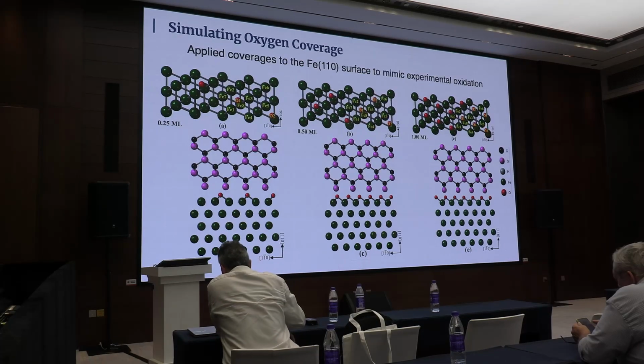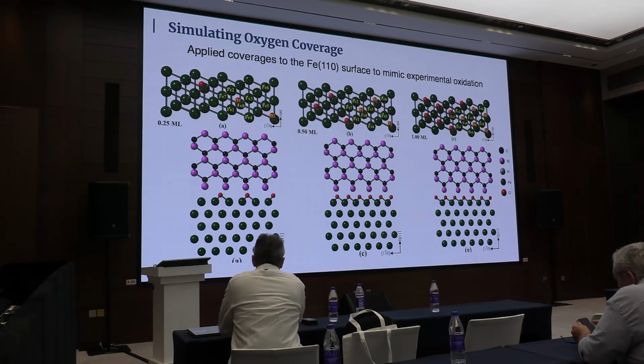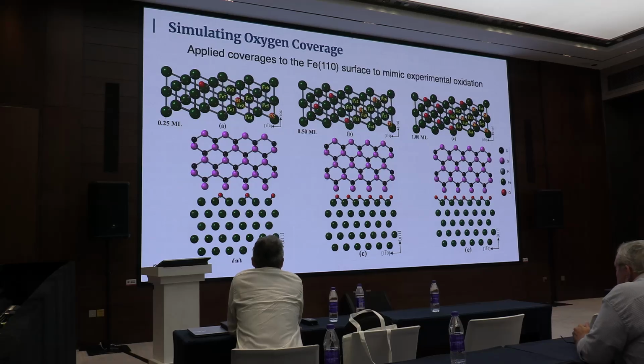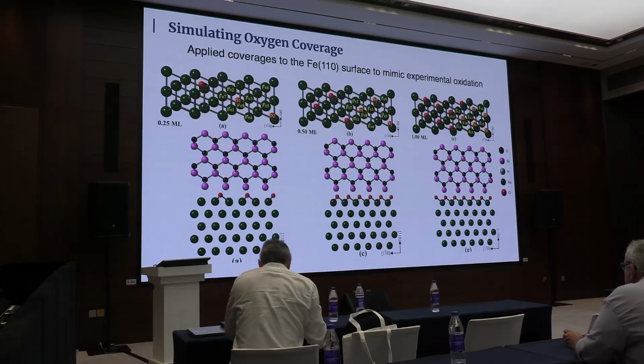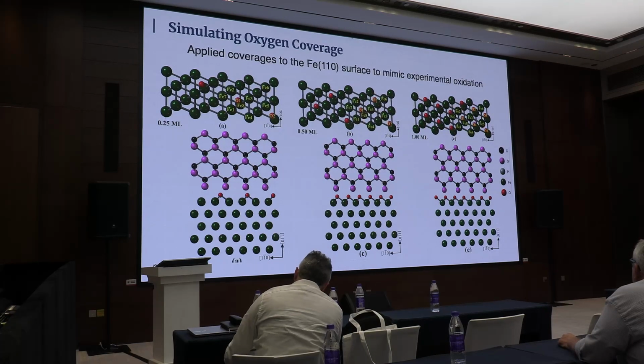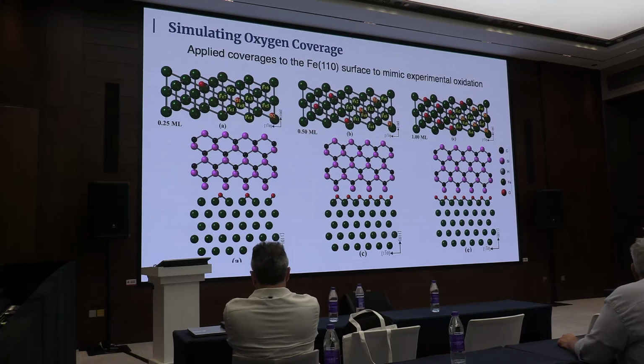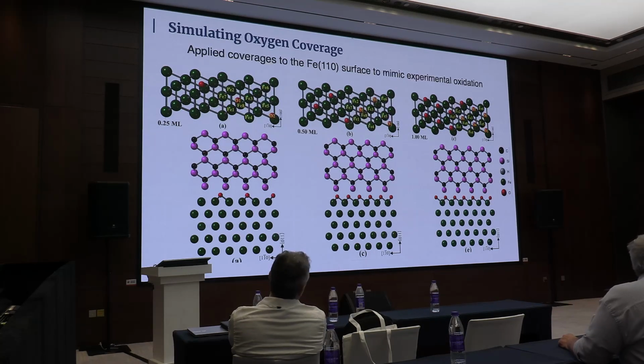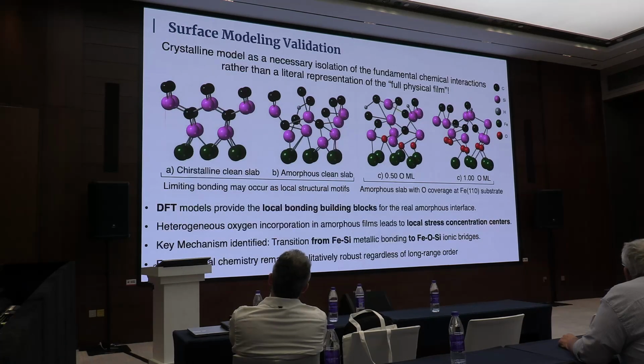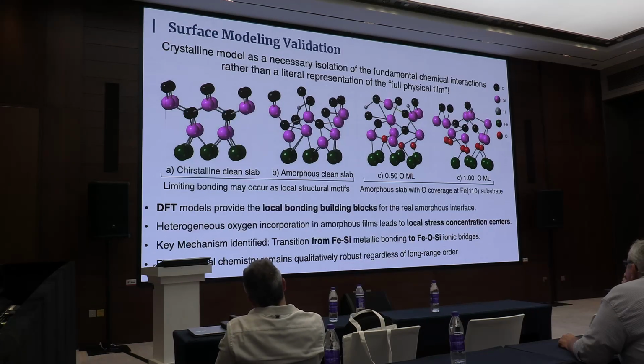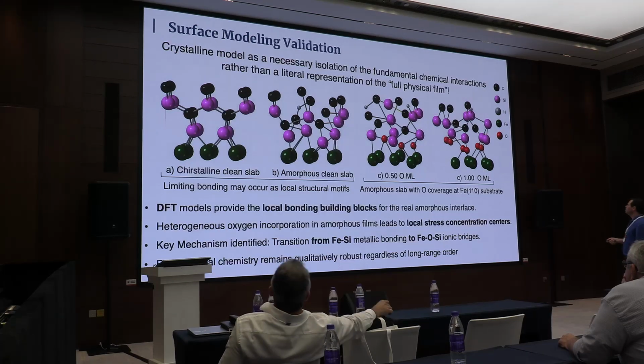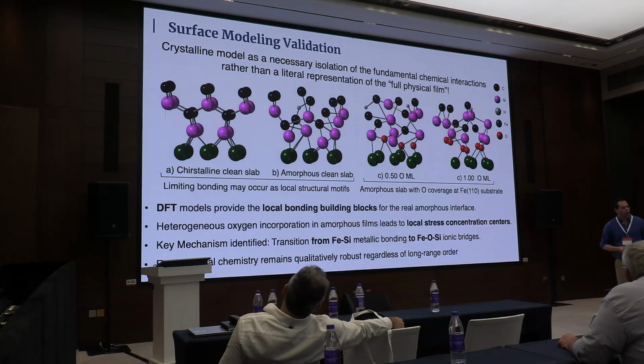Another thing is that we chose a plane called the cleavage plane, which was the most favorable plane and was also known and published. So we chose the most stable one and built the system that way. But this is not the real system we want to describe, because the upper part, the silicon carbide, is amorphous, and now we are using a crystalline one. And the iron we have here is really an alloy of iron, having other atoms there. But if we create an amorphous silicon carbide there, we observe for different oxygen concentrations that the behavior occurs just in the interlayer. And we will confirm this along the experiment.